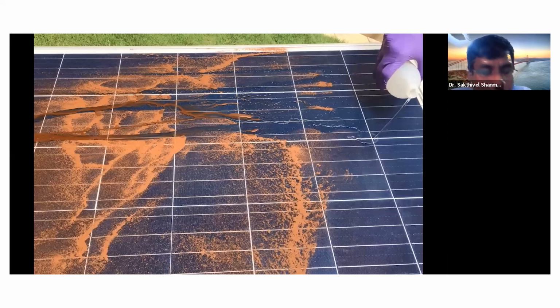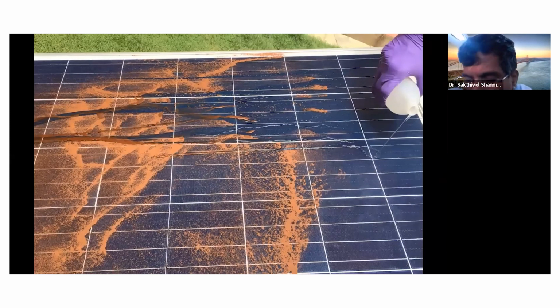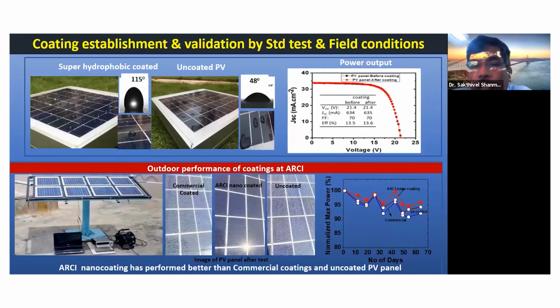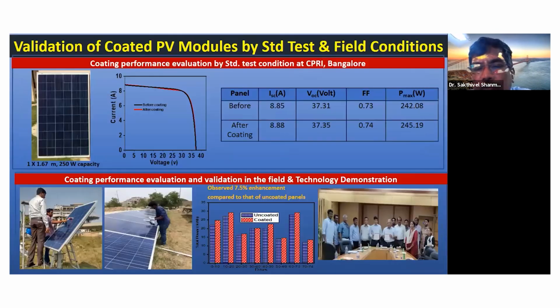So with the positive laboratory validation tests, we applied this coating on the panel at the field level, and we tested this panel for 2 months and observed its high performance. With that positive result, we also validated this coating at the plant level. The plant belongs to NTPC Limited, Noida, and after a 2-month validation, the coated panel shows a 7.5% enhancement compared to the uncoated panel.